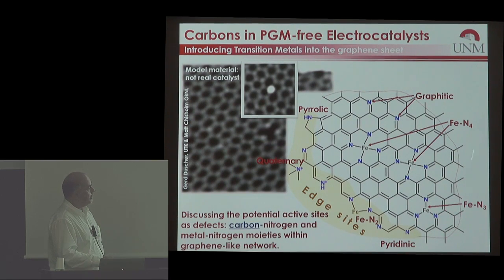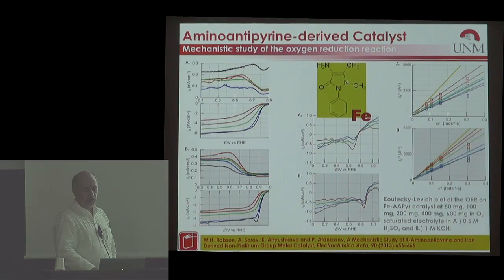The understanding of the mechanism of the oxygen reduction reaction requires us to carry out rotating ring disk electrode experiments. In order to actually prove that the catalyst has 4-electron reduction of oxygen, one needs to carry out experiments of oxygen reduction in a rotating ring disk electrode, record the ring current, record the disk current, this is acid, this is base, and do that at various loadings.